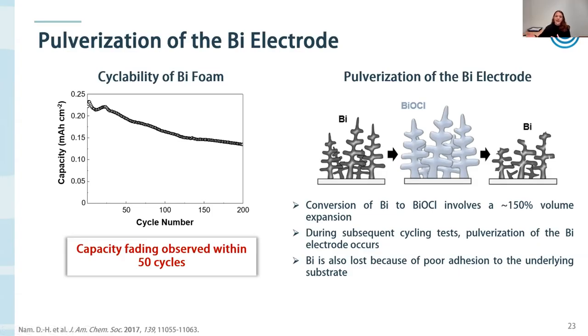And so you can imagine as we continue to use this electrode over and over again, it's expanding and contracting, and expanding and contracting. And we start to see chunks, for lack of a better word, of the bismuth electrode fall off. And for that reason, we see this capacity fading because we're losing our active material. And so our next step in our development process was to try to find another way to make these electrodes so that they were stable for an increased number of cycles.